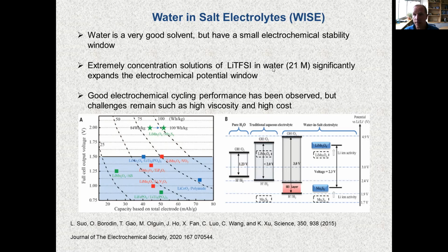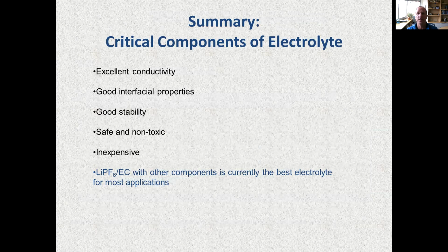At the same time, there is also significant interest in other very concentrated electrolytes where you use very high concentrations of salts in other solvents such as phosphates or carbonates. And there have also been very useful novel properties observed. And once again, for the same reason, because you're basically binding all of the solvent to the lithium salts, and you're changing the electrochemical properties of the electrolyte via that strong binding.